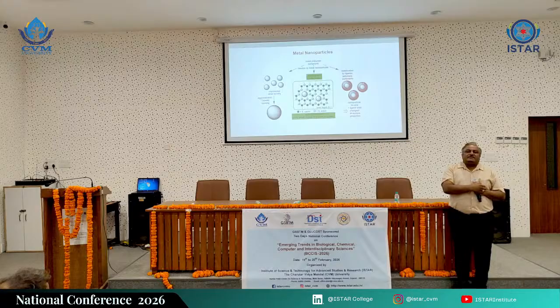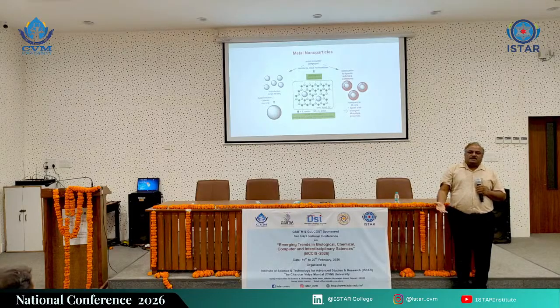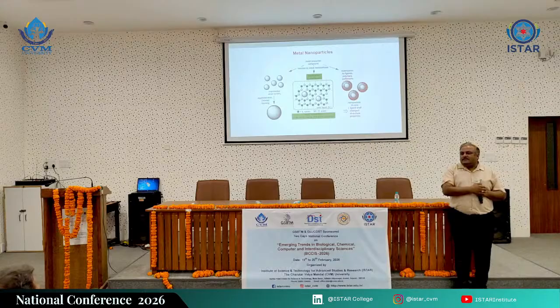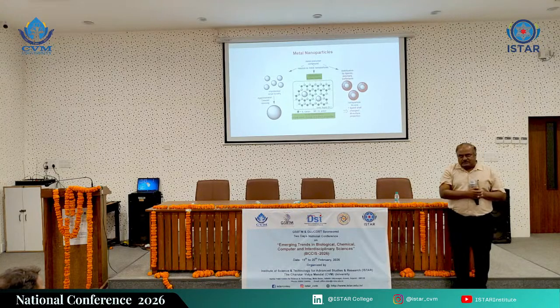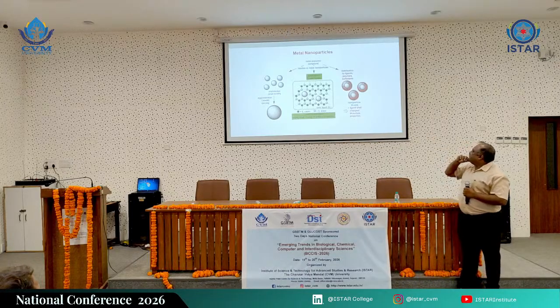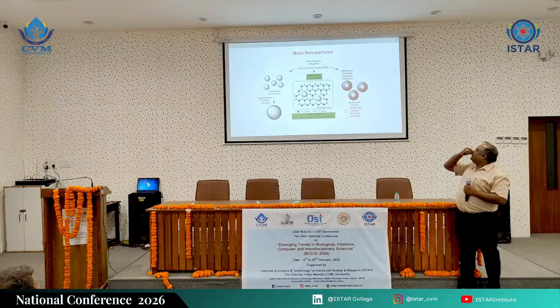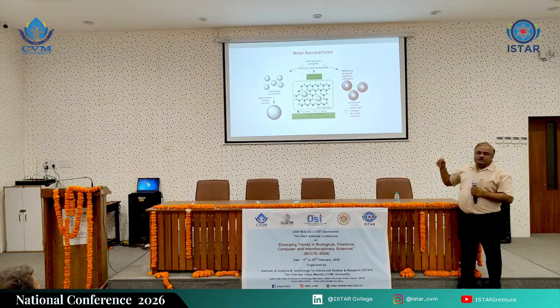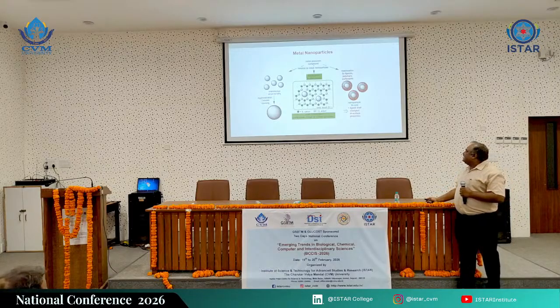But yes, in your application, say for example, I am adding calcium carbonate in rubber. So in rubber, if 800 nanometer or 1 micron calcium carbonate is sufficient to give whatever structural properties they want, opacity and other things, then I don't need to go all the way down to 100 nanometers. So in that case, top down works because it is easier to produce in large scale. But this is an example where metal and metal oxide nanoparticles are started from their precursors. So it is a bottom-up approach, and then we create nanoparticles.